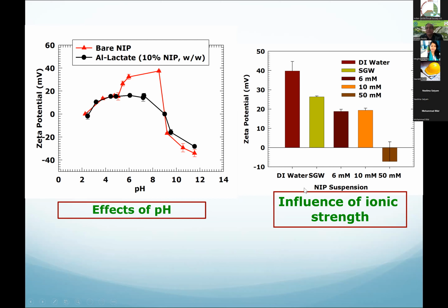Now, what about the ionic strength? If I use deionized water, my zeta potential is this. And if I use synthetic groundwater, we looked at the composition of it, and then we created that one in the lab. And then we used different controlled ionic concentrations, 6 millimolar, 10 millimolar, and 50 millimolar. As you see, deionized water is more positive, and when you use the synthetic groundwater, it is lowered. As the ionic strength increases, it is almost the same, but at higher ionic strengths, it will have a significant impact on zeta potential. But these are all in suspensions.